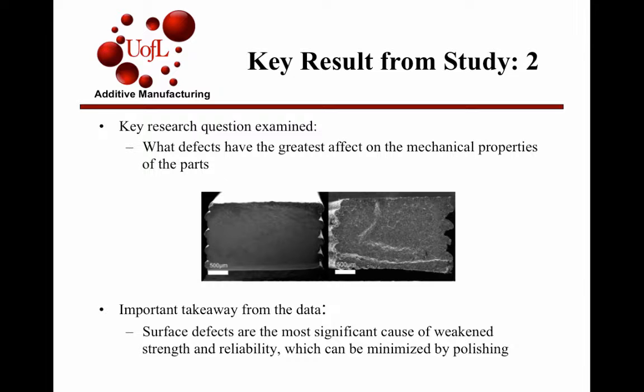Next thing they looked at were the printing defects. Like I said, they just used the scanning electron microscope, and as you can see there, the most overwhelming defect is just the surface defect, which is a product of the way they print these. It's layer by layer extruding this gel out, so it's going to leave those surface ridges. So that's the most overwhelming feature.